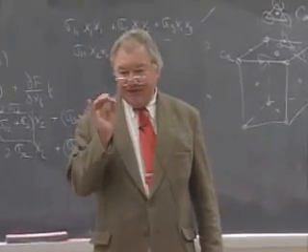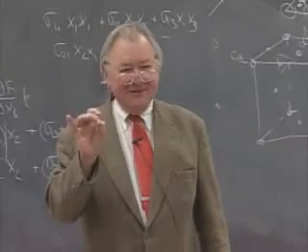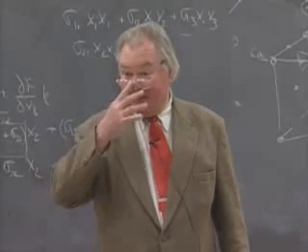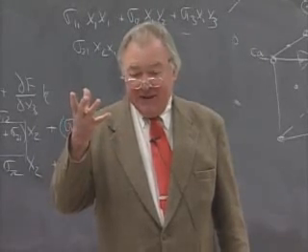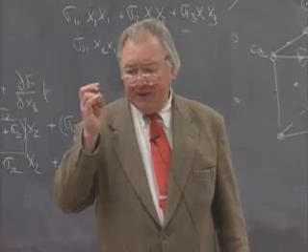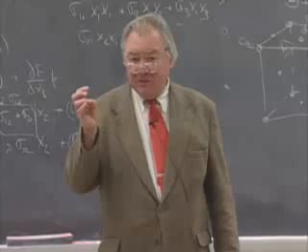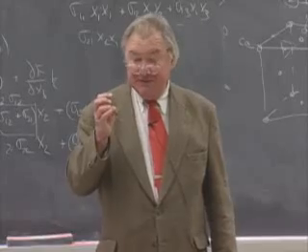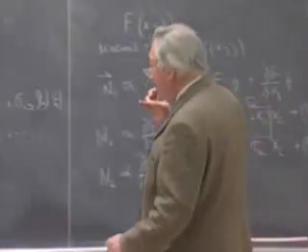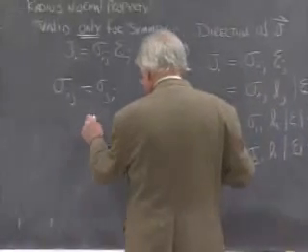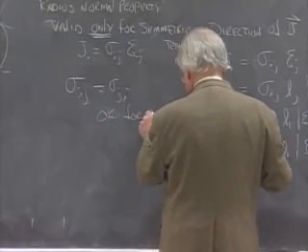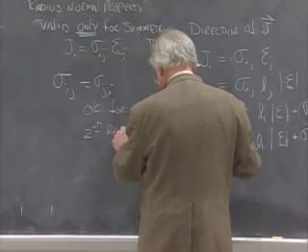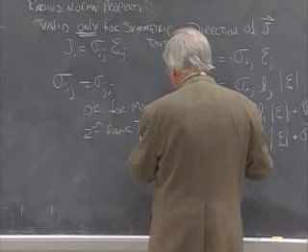And showing that the tensor is symmetric has nothing to do with geometrical symmetry, because it's symmetric in an algebraic sense, not in the literal sense of geometrical symmetry. And there are some properties, the thermoelectricity tensor is one notable example, where the tensor is a second-rank tensor, but it decidedly is not symmetric. So this is okay for most properties. But not all.